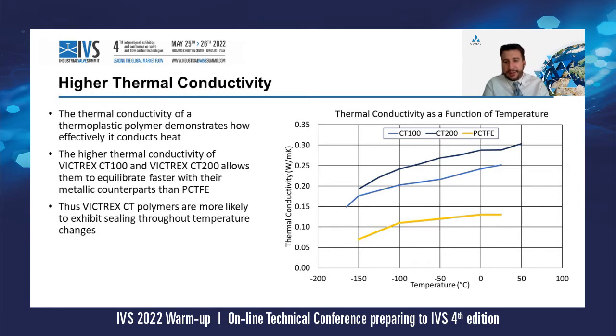So this simply results in sealing consistency, especially while the temperature is going up and down. Your seal will follow its metallic counterpart more rapidly than what PCTFE would do. And this helps to secure your sealing at all times. Again, while for the mechanical properties we have seen CT100 seems to be better, more ductile and more robust than CT200, we can see that regarding the thermal properties, CT200 is actually the best.